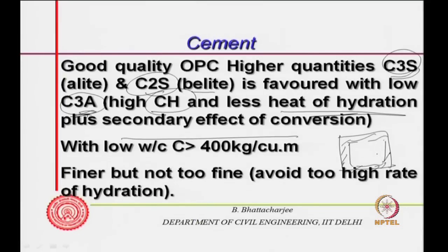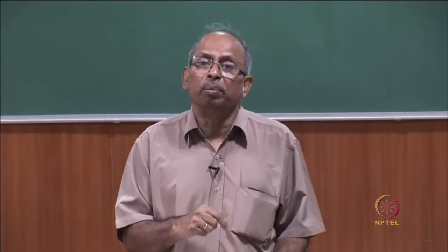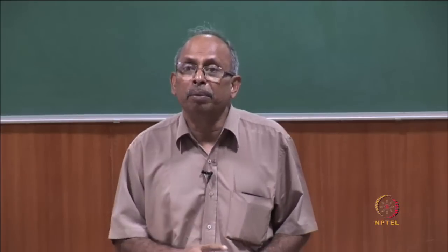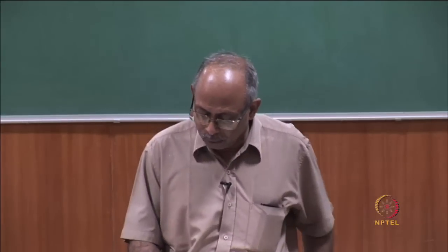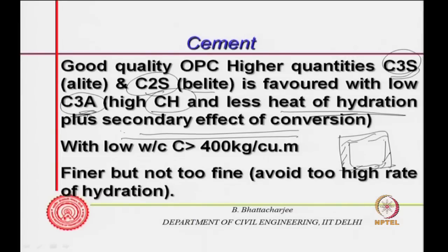Now, they become important in very high strength systems, and may not be as important in low strength systems, because there are already a lot of existing pores of other kinds. But here you are trying to reduce all other kinds of pores, so these pores may become dominant. Therefore, considering the secondary effect of conversion and low heat of hydration, it would be better if you have low C3A content.